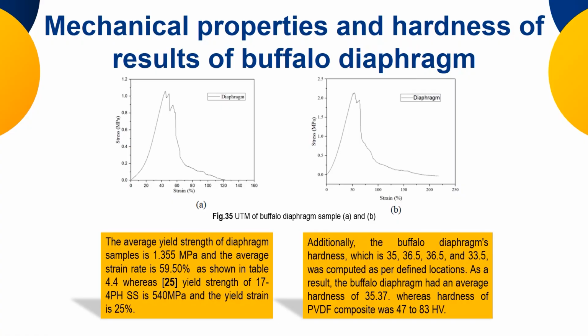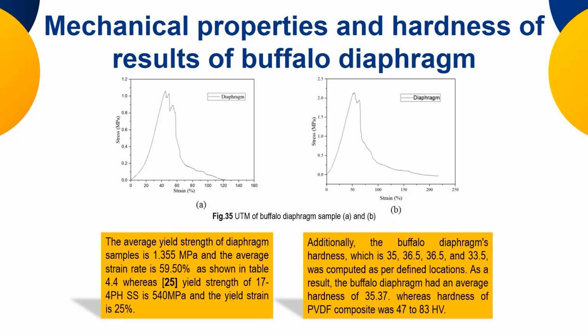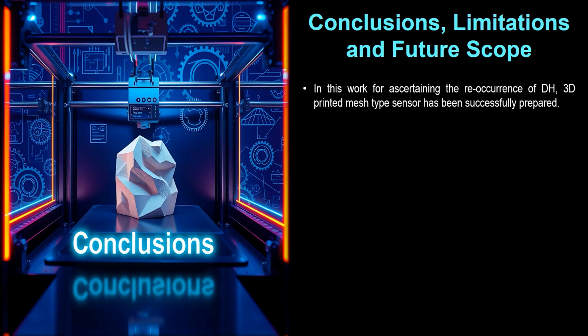Then mechanical testing was also done. It has been observed that the average yield strength of the diaphragm sample was 1.35 megapascal with a strain rate of 59.50%, whereas for the metal part, of course, the strength was much more. We have 540 megapascal, and the yield strain was around 25%. Additionally, the hardness of the natural diaphragm was also observed, and it has been compared, as you can see on the screen, for the polymer and the metal part as well as for the natural diaphragm part. Finally, we were able to fabricate a sensor and see the result in a real time environment.